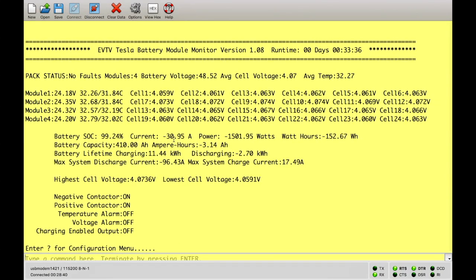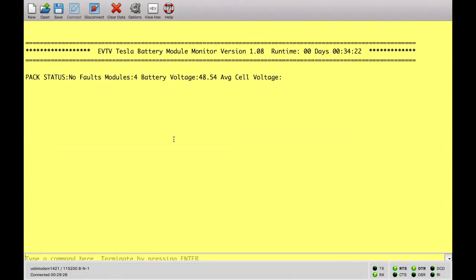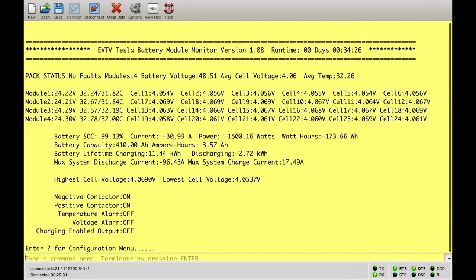And I can show you a little chart here showing the discharge curve of these batteries configured as a 48 volt pack. And you can see that at 40 or 42 volts, we're in our prime here. We're not fully discharged. So you have to oversize your battery pack a little bit using these modules. That's actually not a bad strategy anyway, to never fully discharge your pack and to keep it on the top 2/3 of its operating range. That is actually good medicine in the solar installation and will maximize the life of your batteries. And so that's pretty much okay. But it is the one caveat when using the Tesla Model S cells.